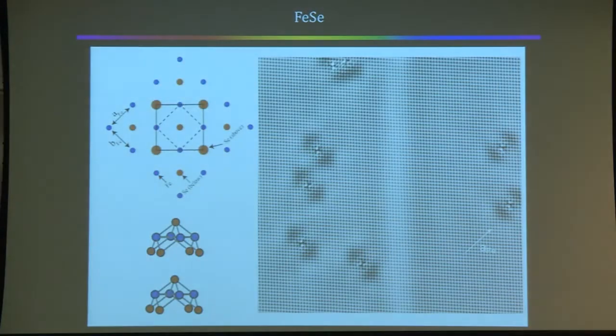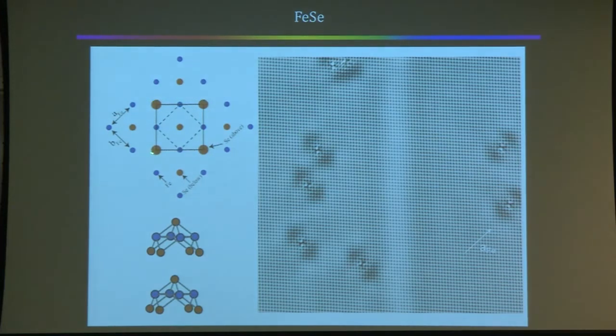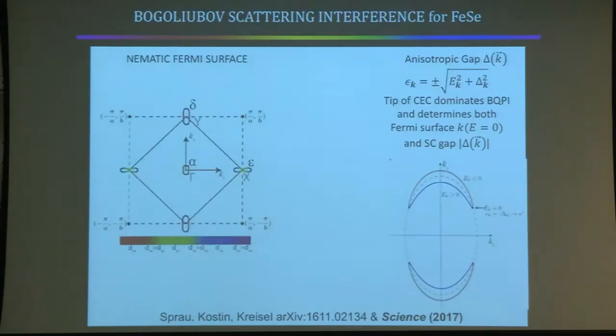Okay, so now how do we visualize this situation? This is the surface of iron selenide. So when you look down on top, you see the selenium atoms. Every dot here is a selenium atom. So that means the iron atoms are diagonal. This is the Fe-Fe axis in this domain, and the Fe-Fe axis in this domain is pointing in that direction. This is a twin boundary. So now we image the quasiparticles in this iron selenide compound.